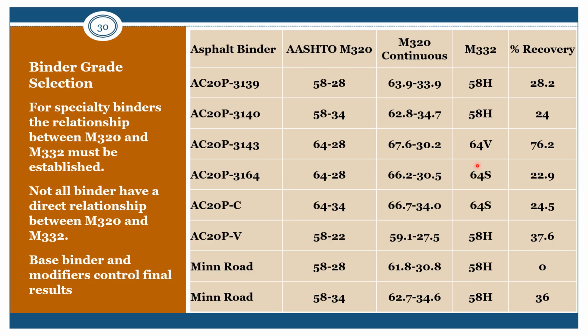And again, you see these two 6428s. One is a 64S, and one's a 64V in the MSCR specifications, where they had very, very similar M320 continuous grades. But you can probably see why you go from an S to a V grade, because when we look at the percent recovery, it is significantly higher for this 6428 as opposed to this one. So this probably had a significant effect on the Jnr value, increasing the overall stiffness of the binder, so that in the M320 specification you would think you were getting the same material, and the MSCR is showing that there is a pretty large difference between these materials. And again, the same thing between this 5828 here and this 5828 here. You can see there are some significant differences between these materials.